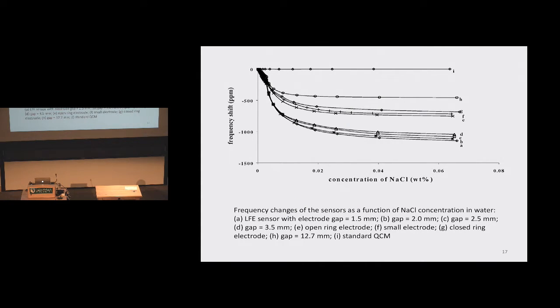All right, here is the frequency changes of a group of sensors. This is the lateral field excited sensor with 1.5 gap, 2 gap, 2.5, 3.5, and now the open ring, small ring, closed ring, etc. And finally, the standard QCM on all of these. This is the gap. You see, this is the standard QCM right up here, responding to concentration of sodium chloride, it could care less. Basically, a conducting solution, the thin film basically shorted it out. So it was incapable of measuring that electrical property.